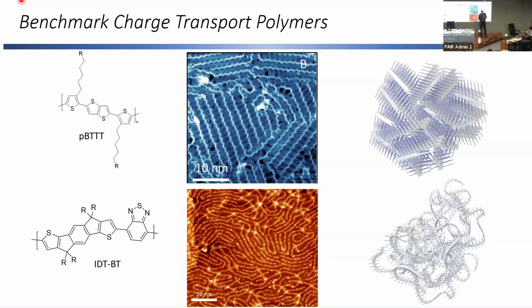Whereas we made this other polymer down here, this is called IDTBT. And IDTBT, slightly lower resolution. You can see there's not much, or what we thought at the time was, there's not much order here at all. You can't see really a lot of interdigitation. There is a little bit of short contact, but at the time we thought this isn't very good. And we thought what happens in IDTBT is the idea that we get this ribbon-like morphology.